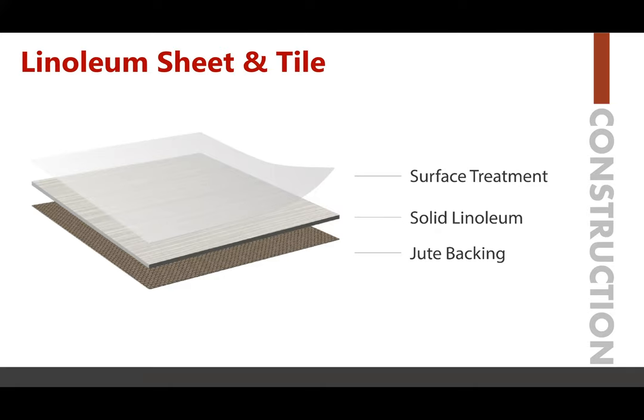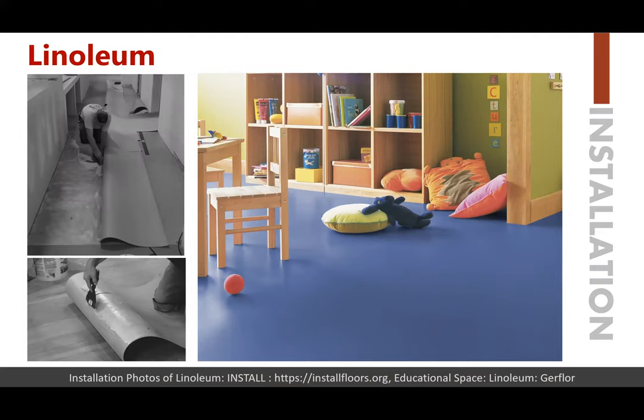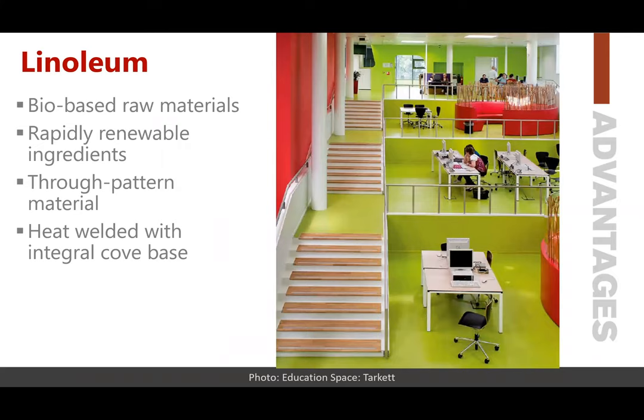Linoleum sheet and tile construction includes a surface treatment, solid linoleum, and jute backing. Linoleum installation does, in some cases, require more knowledge and advanced installation skills. The material has a propensity to expand in width and shrink in length when rehydrated in adhesive — there are techniques that mitigate that movement. There is also end-curl memory: due to drying the material and rolling it in packaging, the ends of each cut must be worked out prior to installation to break the memory and allow the material to lie flat. When qualifying subcontractors, you'd want to verify familiarity with linoleum. Advantages include bio-based raw materials, rapidly renewable ingredients, through-pattern material, and like other sheet products, it can be heat welded with an integral cove base.